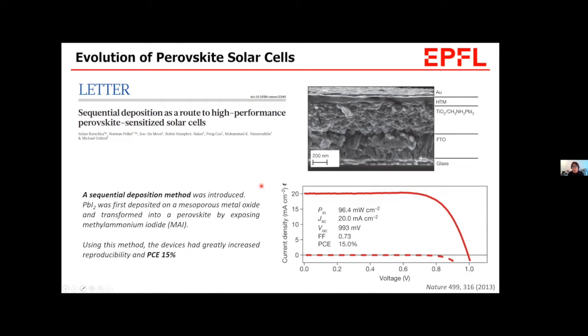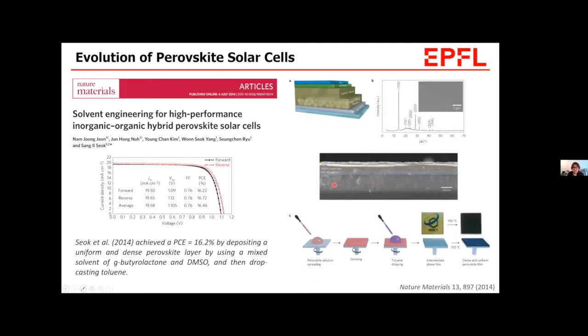In the one-step process, we put all the precursors together in a solvent to dissolve. But in this two-step process, lead iodide is first deposited, and the subsequent deposition of ammonium halide on the lead iodide causes a reaction that crystallizes the perovskite. Using this method, they achieved 15%. So here again, this is a one-step process, and you can definitely differentiate this additional layer, like a bilayer type layer.